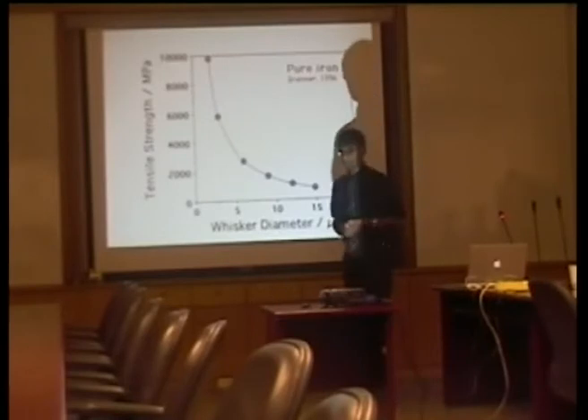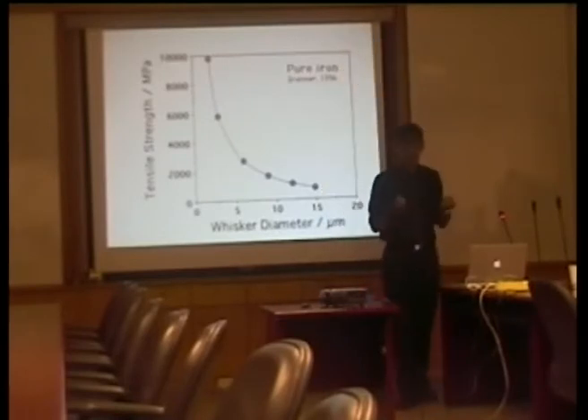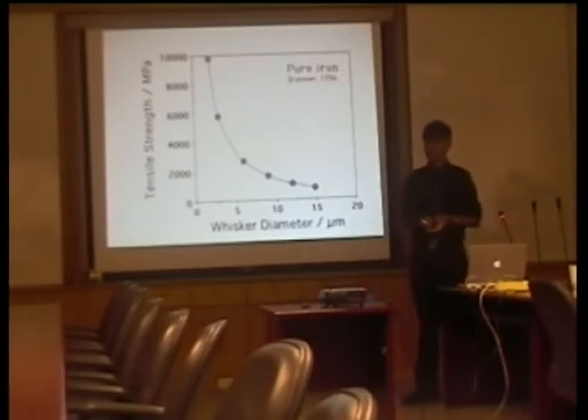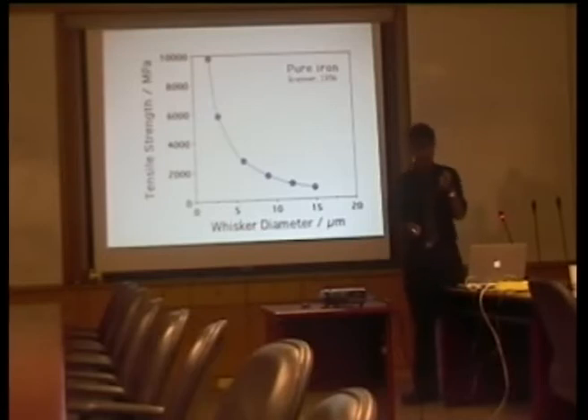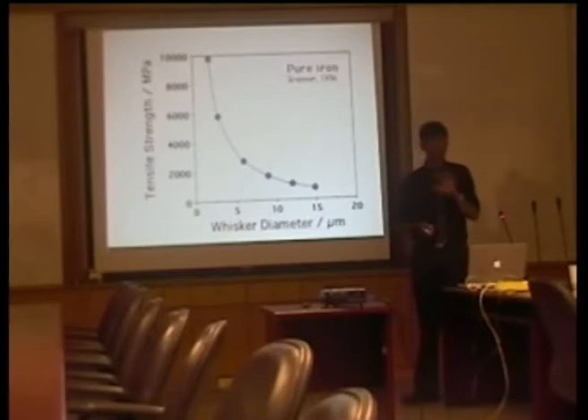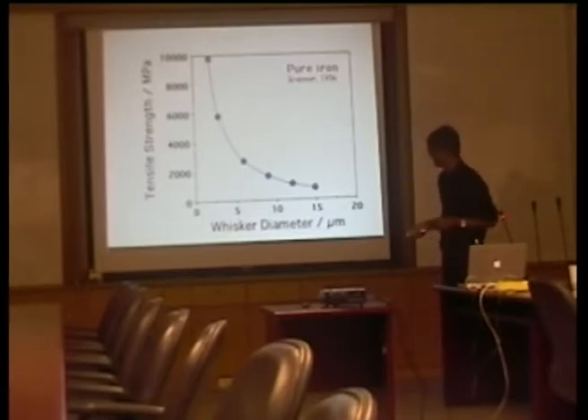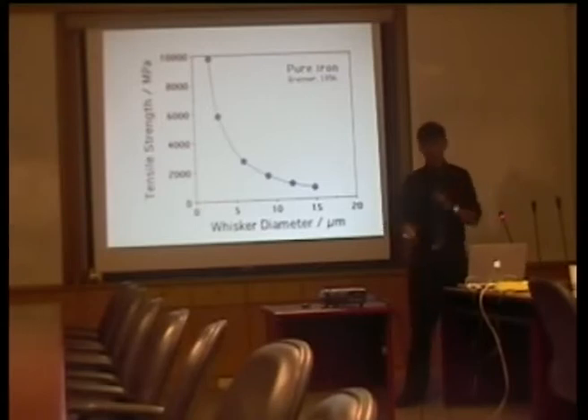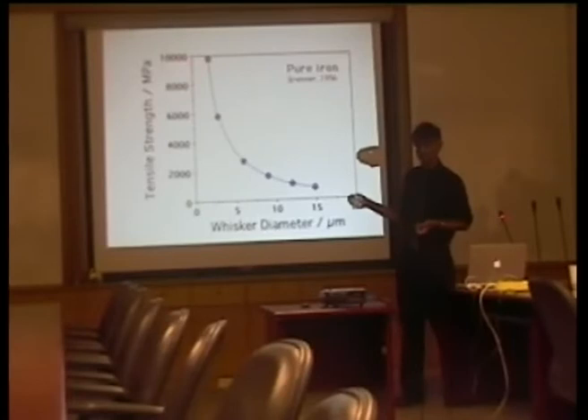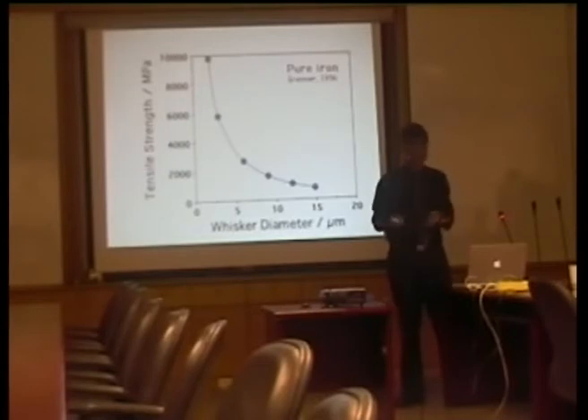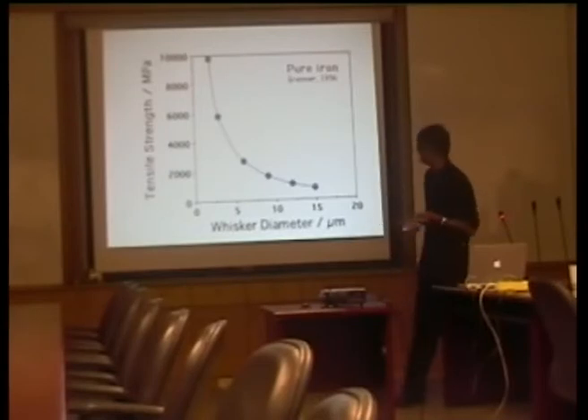Right. So, first of all, let's just think about how strong iron can be in theory. If you go back to 1956 and just look at pure iron, without any alloying additions, if you make a single crystal, which is about 1 micrometer in size, then you can already in 1956 get a strength of 10 gigapascals, 10,000 megapascals. That's a very, very strong material.